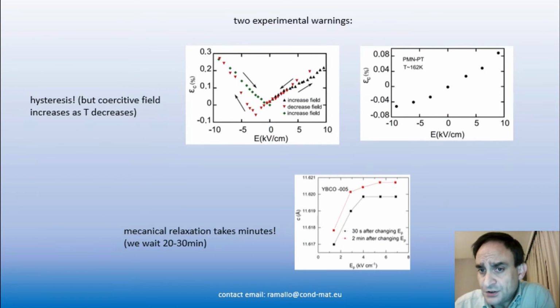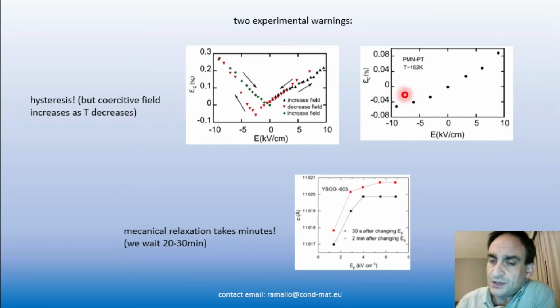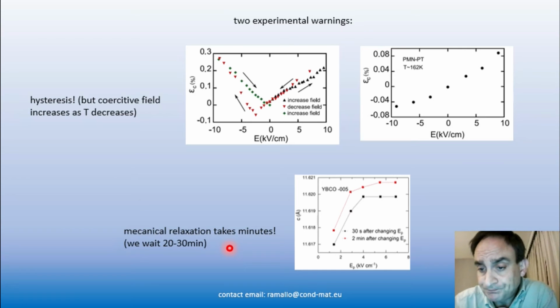And you soon discover, for anyone wanting to reproduce these experiments, two experimental warnings. The first is that the process has hysteresis, the piezoelectric has hysteresis. So decreasing and increasing the field, you have to take that into account. Fortunately, as temperature decreases, the coercive field increases, so there is an ample region in which the system is just linear with no hysteresis, so that makes things much easier. And the other warning is that mechanical relaxation is not instantaneous, it takes minutes. So we wait at least 20 to 30 minutes until relaxation is stable.